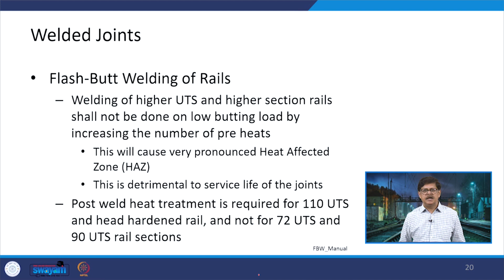Now, welding of the higher UTS and the higher section rails shall not be done on low butting load. So if we are talking about higher UTS rails, a low butting load should not be used, and we should not say that we have used a low butting load and at the same time are increasing the number of preheats. This is a bit detrimental to that weld. So this will cause what? This will cause a very pronounced heat affected zone, and this is going to create a problem in terms of service life, because that particular zone will be more prone to certain types of distresses or defects which can appear over time. Now, post weld heat treatment is required for 110 UTS as well as HH rails, whereas in the case of 72 UTS or 90 UTS rail sections, this post weld treatment is not required.